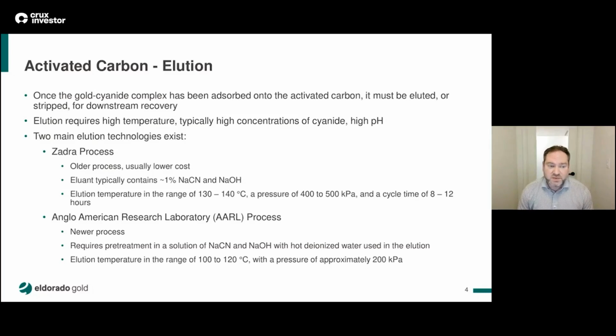So looking at elution, once the gold cyanide complex has been adsorbed onto the activated carbon, we have to elute or strip it for downstream recovery. Elution typically requires high temperatures and high concentrations of cyanide, pH, and pressure. So the two main technologies that are used for elution are the Zadra process, which is the older process, somewhat lower cost, and typically favored in North America.